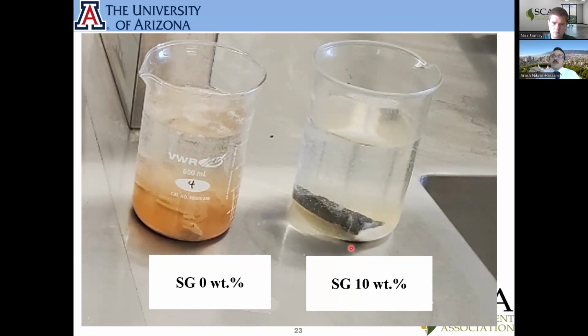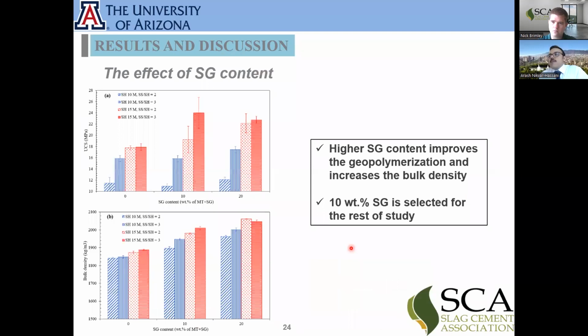Even after we crush the sample and put just the crushed sample, so even the core of the material is exposed to the water, it's still keeping its integrity. So now we try to see, okay, slag is good, so how much slag do we need to add? We check the slag amount and we used 0, 5, 10, 15, 20, but here I'll just show you some example of the data. We show 10% and 20% of the slag.